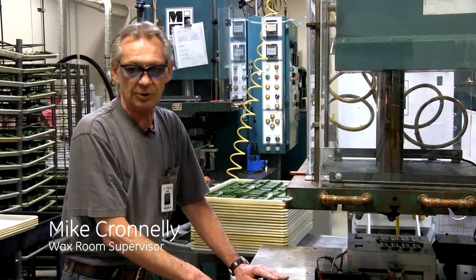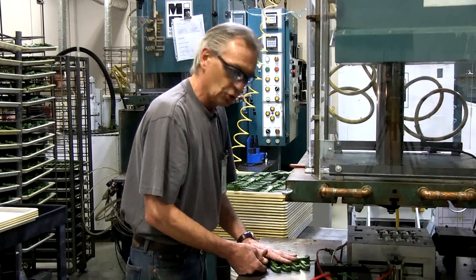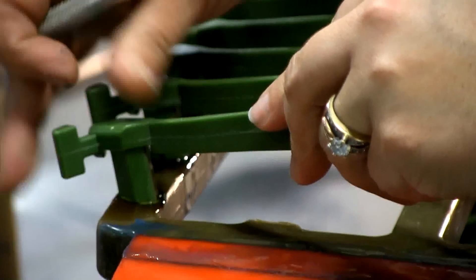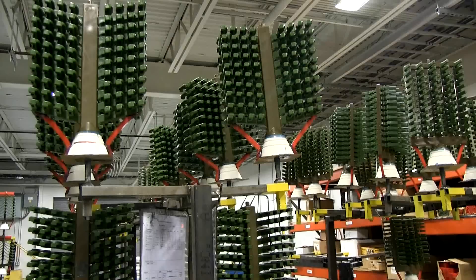In the wax room, there are essentially two operations. The wax is at 145 degree temperature, and it's forced into the mold, so we take it out, inspect it, let it cool down some more, and then go on to make another part. Then we take usually multiple of these wax patterns, and we mount them to gating infrastructure, what's known as a tree.